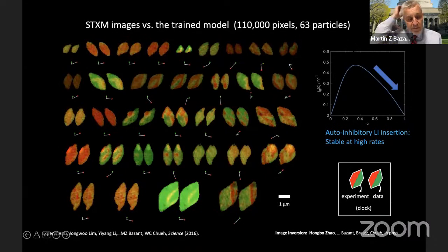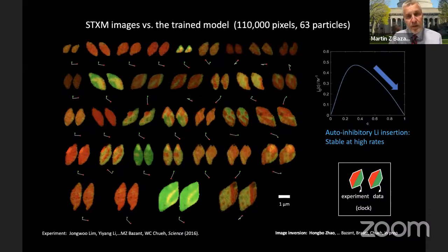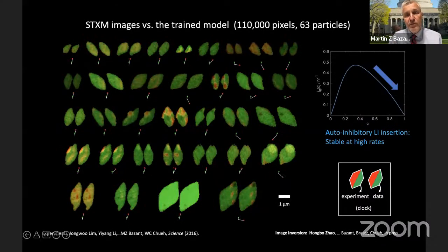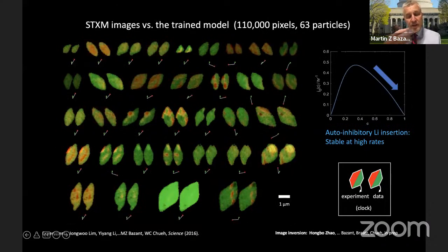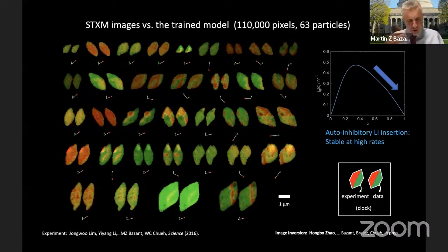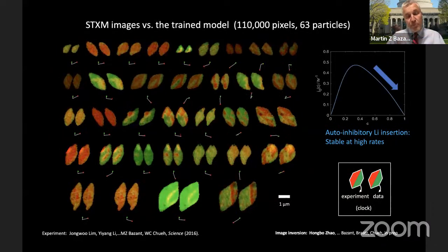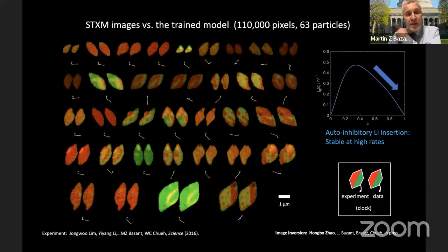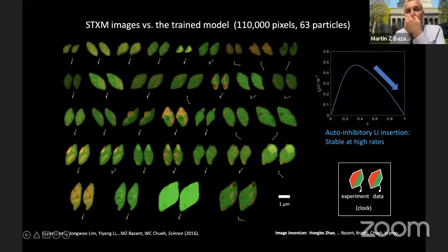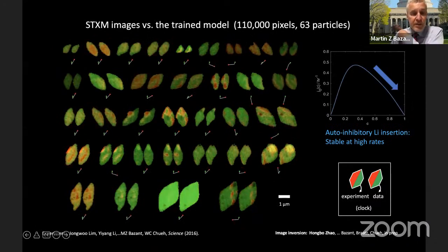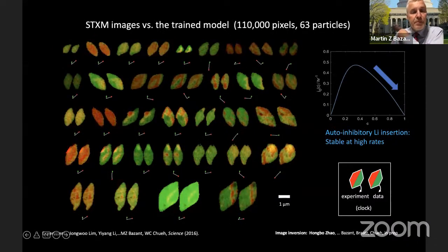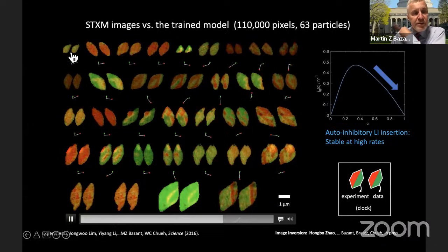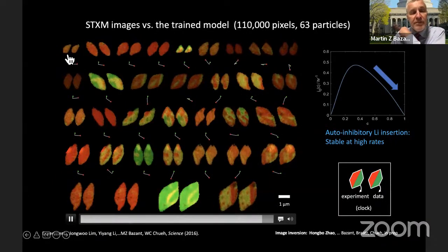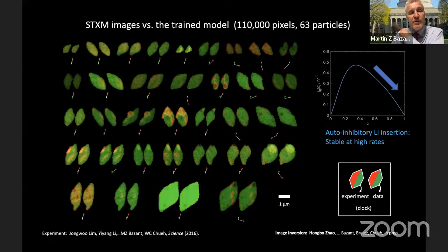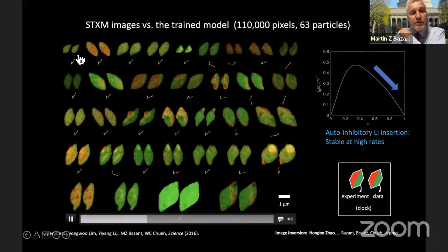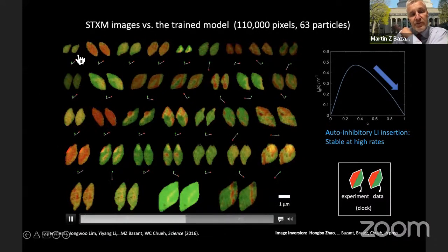So we had from the original experiments data for 63 particles cycled in and out of lithium over a number of different currents, each at different rates. And so it totaled over 100,000 pixels of good data that we ended up keeping and using. And what you see here, each of these pairs of images, on the left is the experimental image, and on the right is the learned simulation for that specific particle.